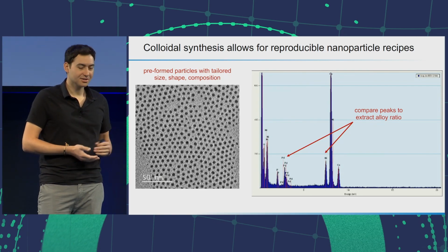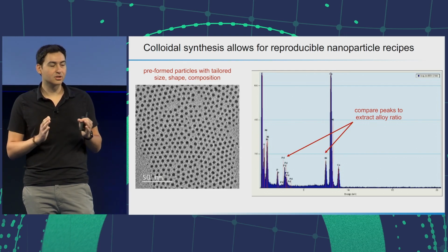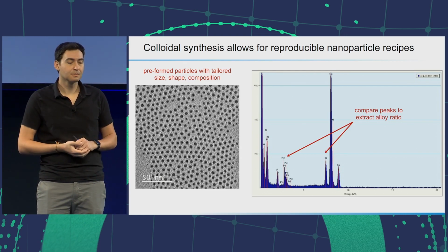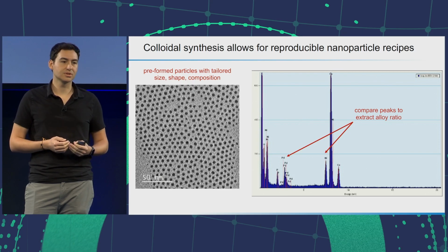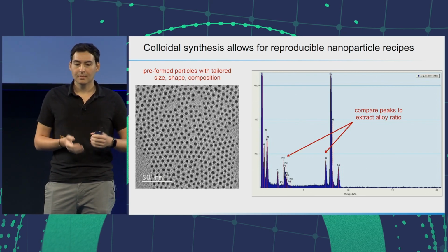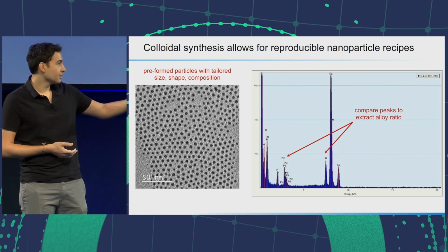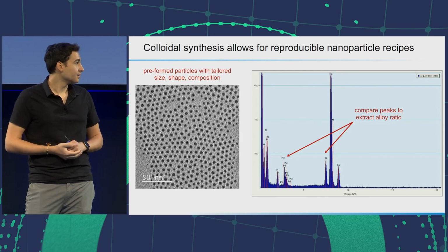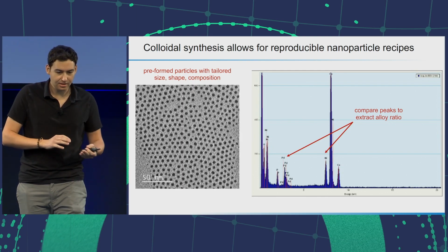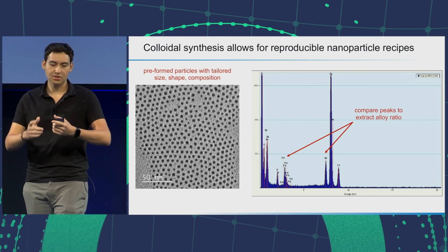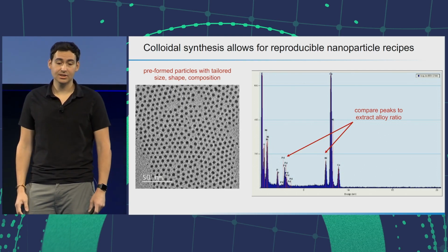If you want 7 nanometers, we'll grow them all 7 nanometers. We really have control over the size distribution here. And we can tailor the nanoparticles in terms of composition, shape, et cetera. And so what you're seeing here is an EDS spectrum of the different components. So this one is a palladium-nickel mixture. And so by measuring the ratios, we can tell what that composition is.